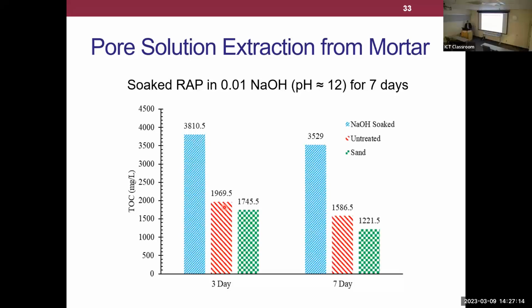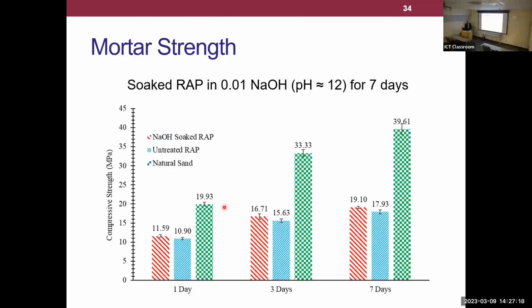So yeah, unfortunately, it didn't work. But some interesting stuff's going on here now. If we then test the strength of that mortar, we actually did see, you can see there's a very slight difference here. So this is the pre-soaked RAP, this is the unsoaked RAP. Slight increase in strength.